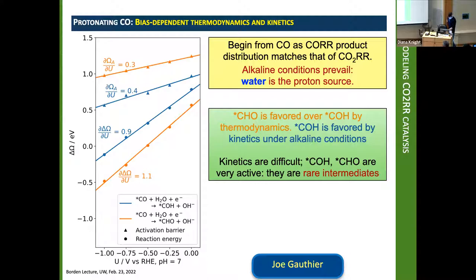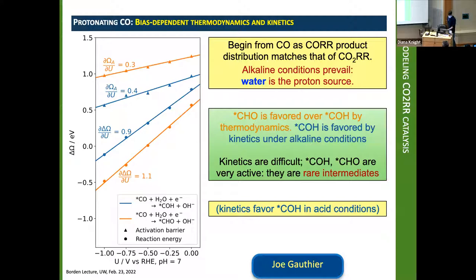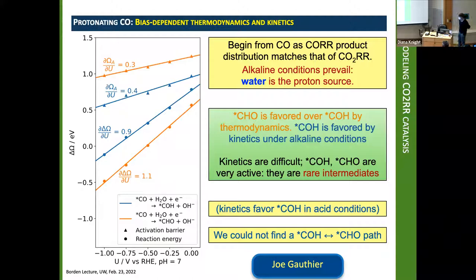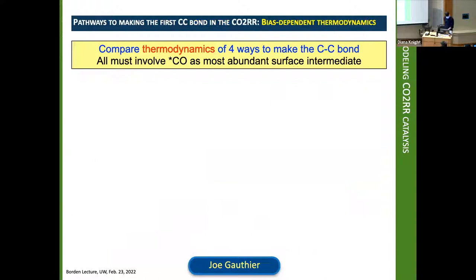The kinetics favor *COH in acid conditions as well. And we couldn't find a good COH to CHO interconversion pathway that doesn't just involve going back to CO and starting again. Maybe it's actually surface-bound hydrogen that's responsible for making *COH, *CHO by a more viable pathway. Okay, so that's the protonation of CO, and it's an illustration of what we can calculate.